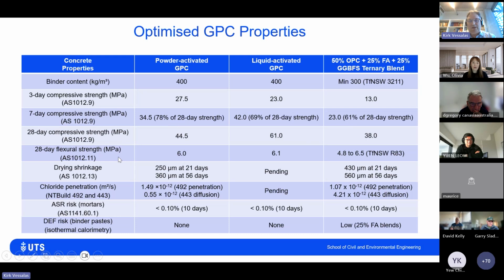We're also able to meet flexural strength requirements of Transport for New South Wales R83, which applies to pavements. And drying shrinkage, as I mentioned before, is pretty impressive. In fact, it's much lower than conventional ternary blends. The chloride penetration, whether we're doing the Nord test 492 or 443, chloride penetration, chloride diffusion, these results, particularly the 443 result, is very impressive. 0.55 by 10 to the minus 12 compared to 4.21 by 10 to the minus 12. The ASR risk is very low. Expansions are less than 0.1% after 10 days. As I mentioned earlier, the risk of DEF is mitigated when using a powder or liquid activated GPC system.